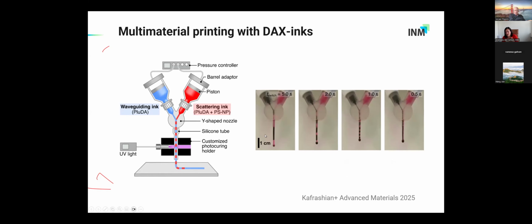We can print pluronic, as I said, to make the side emitting fibers, as I told you in the design at the beginning. We need to use a multi-material printing approach in which we alternate inks. The ink that has waveguiding properties, this would be the pluronic, and the ink that combines the pluronic plus scattering nanoparticles, it would be the scattering ink. And you see, this is an example. These are these 2 inks, with color to see them, and you see that we can actually alternate them depending on the switching between these 2 pistons or these 2 containers. For the printing, we can switch them, and we can get continuous threads with alternating composition.